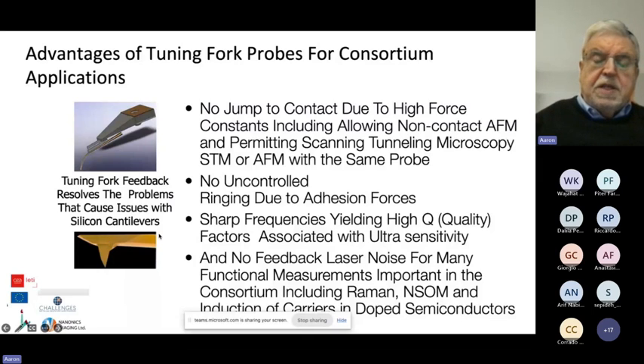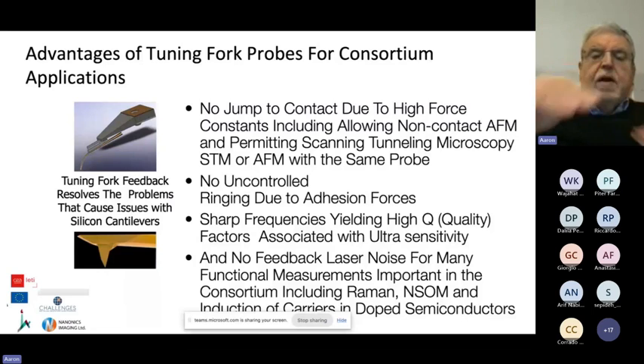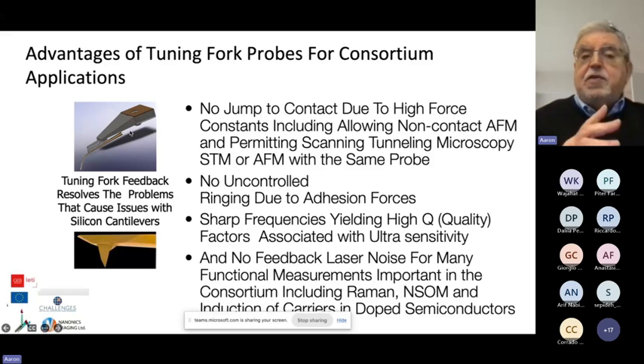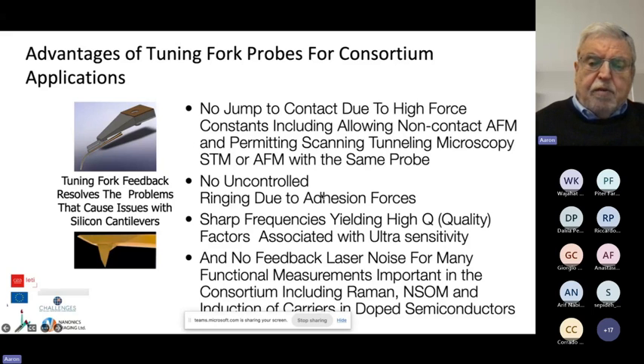So when you come very close to a surface, there is a jump to contact of the system. And so basically, you cannot keep a probe even a few nanometers from a surface with such a probe. With a tuning fork, you can bring it to less than an angstrom, and it will not touch the surface. And therefore, you can flip between STM and AFM. And this has been shown with this system too. This is more about the uncontrolled ringing of the adhesion forces. This is more concerned with elasticity, and I won't go into that right now.